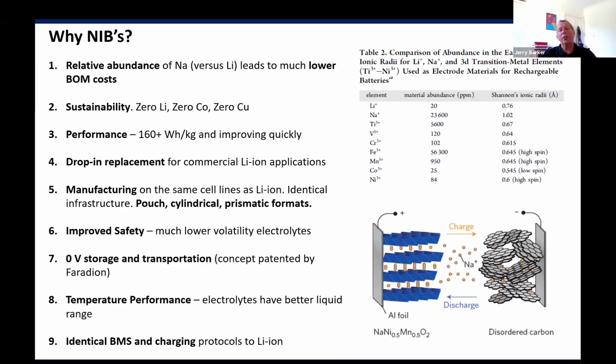Performance, right? We normally talk in terms of energy density or specific energy. So Faradion cells right now are running at about 160 watt-hours per kilogram. But we're improving that figure quite quickly. And that's pretty good, right? If you know these figures, 160 watt-hours per kilogram puts us pretty well on a par with good lithium iron phosphate. But things like lithium iron phosphate, I've worked on lithium iron phosphate for a very long time. Lithium iron phosphate is a great technology, but it's a mature science now, right? There isn't much more improvement around the materials and the chemistry.